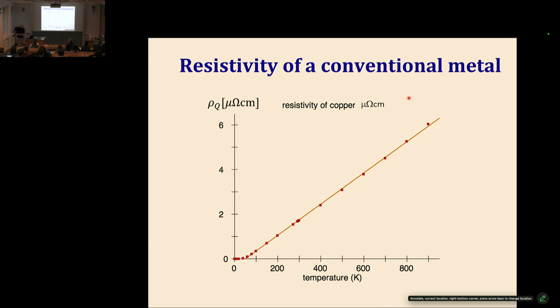So here's the resistivity of a conventional metal. This is copper as a function of temperature over a very wide temperature range. Okay, and you can understand this curve from Fermi liquid theory plus Boltzmann transport theory in great detail. You see different behavior at high temperature and at low temperature, and just by fitting a few experimental parameters, you can understand this curve. The fit is to Boltzmann theory.